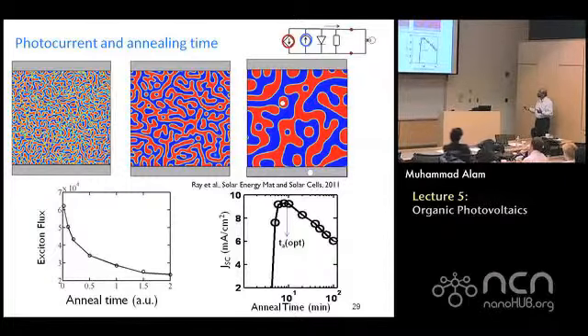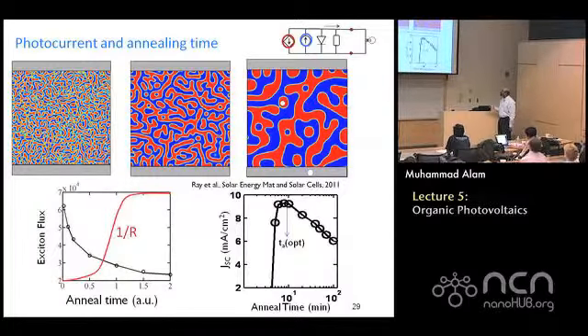So this is a percolation problem for electrons and holes, and so you get a lot of exciton dissociation, but as the electrons are trying to find their way to the other side, lots of holes are also trying to find their way to the other side, a lot of recombination, and as a result, you really do not get much out to begin with. By the time you come about here, it nicely balances the exciton dissociation with the electron hole transport. You have a maximum efficiency, a maximum short circuit current. And then if you stay too long, these regions get so thick that charges get out very nicely, but excitons don't get dissociated very effectively, because these regions are thick, you are losing a lot of excitons. So this is a trade-off between resistance and current collection versus exciton dissociation that defines the maximum.